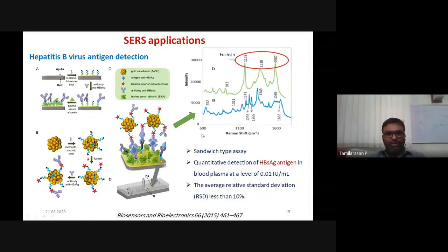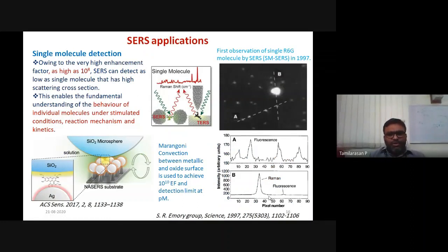If there is no antigen corresponding to hepatitis B, then you will see a Raman spectrum something like this, which is corresponding to the presence of native organic stuff like bovine serum albumin and so on, other antibody and so on. But if you have any antigen, then definitely your fuchsin will be present here. So you will see strong peaks corresponding to fuchsin. So in this method, you can get the detection level as low as 0.01 international unit per ml with a very good RSD value of less than 10%. And another application for this SERS substrate is single molecule detection.